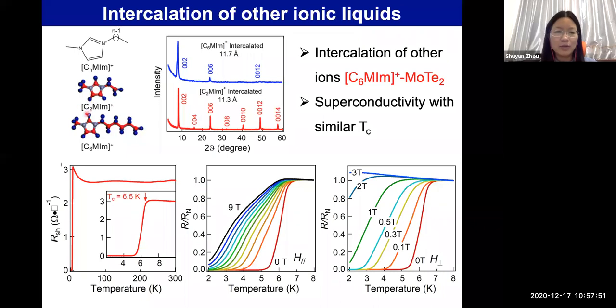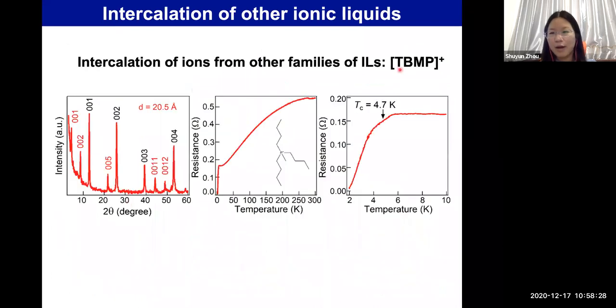So here we try to use a different size of cations in the ionic liquid, but they are still in the same family, with different lengths of carbon chains. Here we can see that these cations can also be successfully intercalated into molybdenum ditelluride, and we can also see superconductivity with a TC of 6.5 Kelvin. Even if we try other families of ionic liquids, we find that we can also intercalate these cations into the layered material, and here the TC is somewhat different.